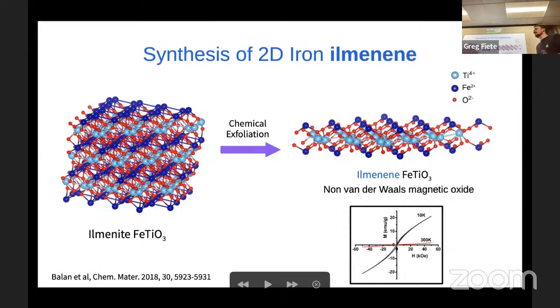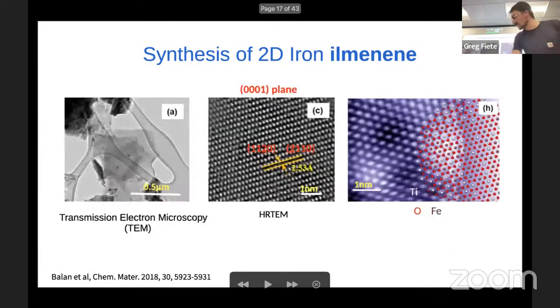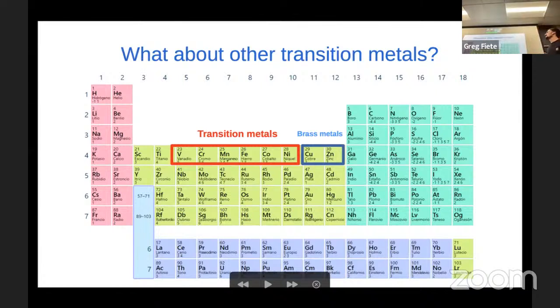Since it has been realized experimentally, let's talk a bit more about this compound. They did some transmission electron microscopy measurements where single and two-layer zones of ilmenene can be observed. They also found that this compound exfoliates in the 0001 plane, the hexagonal z-axis. So this compound was experimentally synthesized, and we were thinking about other transition metals. We have observed that cobalt titanate, which is similar to ilmenite in structure, is already interesting in bulk. So what's happening with similar ilmenenes in the two-dimensional regime?